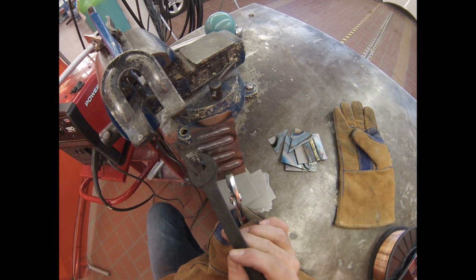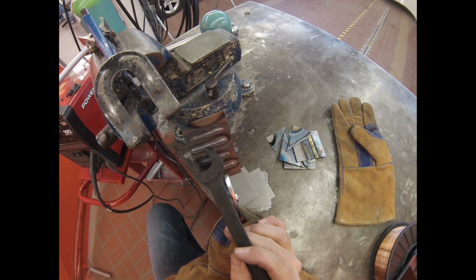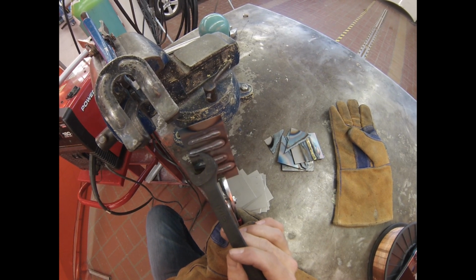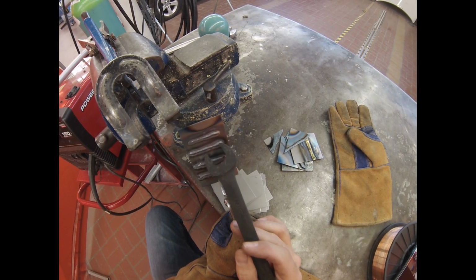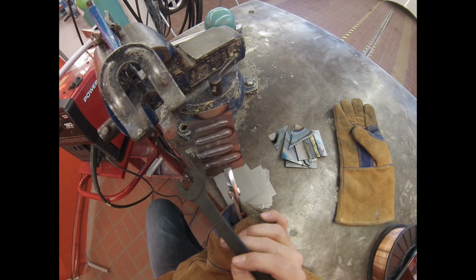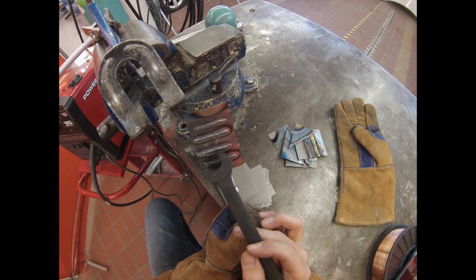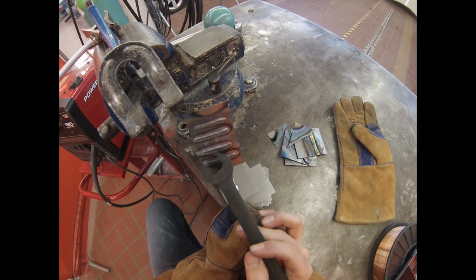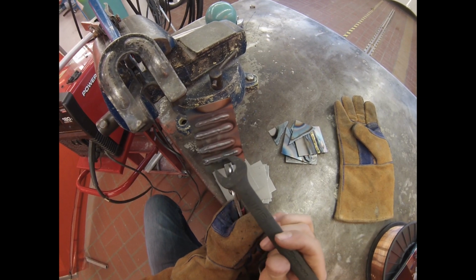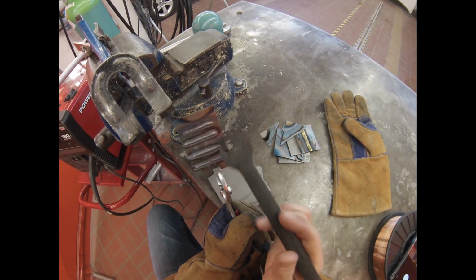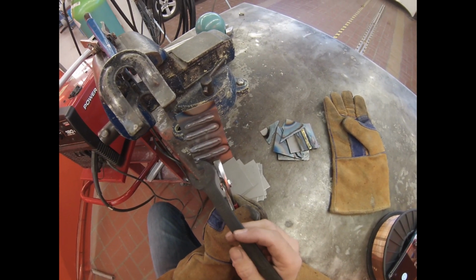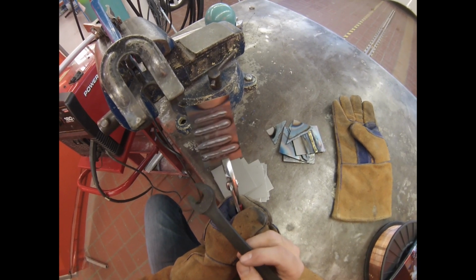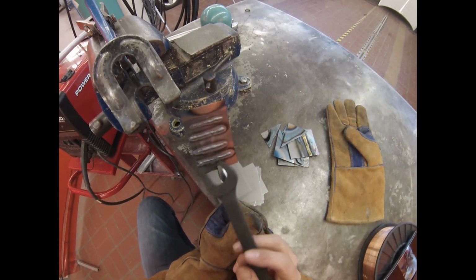This one here was the pull. You can see the pull is more consistent as we go across, and then you can see a little extra penetration at the end. This is the push, and you can see it's a little bit fatter, a little bit wider, and then this is the pull going back. And you can see those last 2 that I did have very similar heat in the coupon, very, very similar travel speed and everything too. And you can see the welds look different.